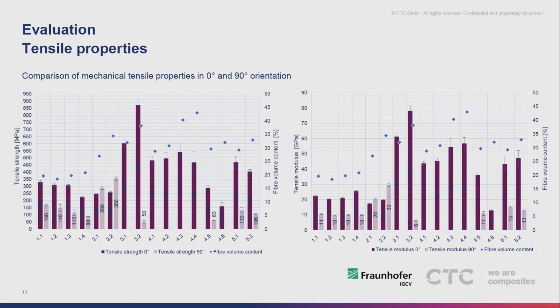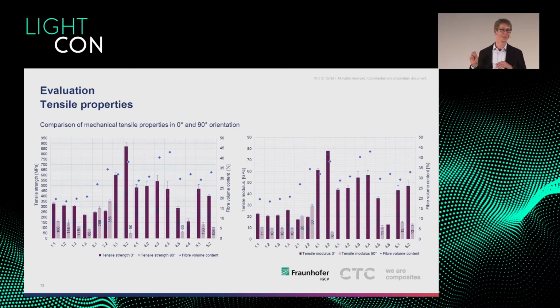And that's one of those technologies where you are producing a carded sliver, basically exactly what the cotton industry does. You're producing a thin strand of non-oriented, just slightly bound together fibers. You add a lot of thermoplastic fibers and thermoplastic material to that, which enables you to subsequently do a very, very high degree of stretching to the yarn that you have in front of you. And with that, and this is only the, let's say, 1-year-old data, we achieved, like last summer, around 900 megapascal on average for these materials. And by now, just to add on that, 1050 megapascal has been the average of the most recent trials, developments of these carded yarns. And that actually is a 10-fold increase of the performance compared to what we are used to seeing in nonwovens. And that actually allows us to bring these materials much more into view.